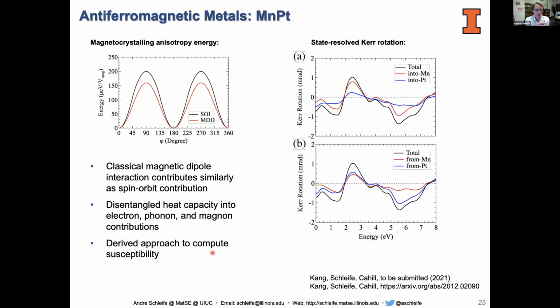Maybe I'm wrong. My recollection is the moments in manganese platinum, which is FCC, lie in the 1-1-1 plane, so there should be a 6-fold anisotropy axis. You appear to show a 2-fold anisotropy. How is that? Right. So we certainly didn't see a 6-fold anisotropy, but I'm happy to look at that with you if you find it to be 6-fold. It is a cubic material, that's for sure.